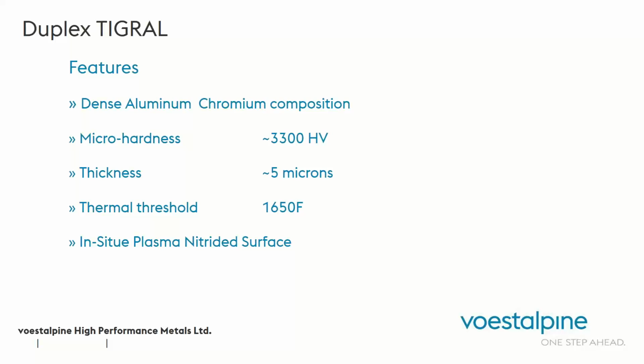Okay, so now we get to the Duplex Tigral. Features of Duplex Tigral. It's a dense aluminum chromium composition, as I indicated, and that's important to make a stable coating that's chemically inert relative to your aluminum alloy. So when I say chemically inert, it doesn't react with your aluminum alloy. It's got a micro hardness of 3,300 Vickers. Put that into perspective, your hardened steel surface is probably less than 600 Vickers, so substantially harder. Thickness is only 5 microns, 5 or more, depending on the size of the part and configuration of it.